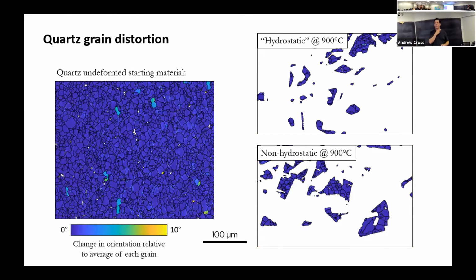And we can think about how those two phases are accommodating the phase transition by thinking about how internally bent and deformed those crystal lattices are. So what's being shown here is, for a given grain, made up of a lot of pixels, a lot of analysis spots, we calculate the angle between each pixel's orientation and the average of the grain. If the coloring is blue, it means that within a particular grain, the lattices are completely uniform in orientation. When you get hotter colors, it means that there's some local bending of lattice.